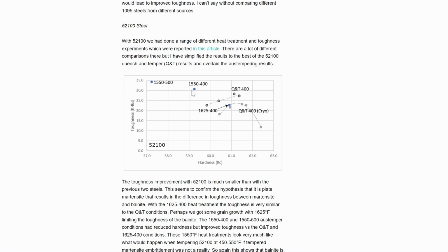But if I austenitized hotter to get higher hardness with 1625, then the hardness got higher, but then it looks very similar to the hardness-toughness balance of normal quench and temper. So Austempering can be useful for intermediate hardness ranges, let's say for axes or really large knives. But for thin cutting knives, quench and temper is usually the way to go.